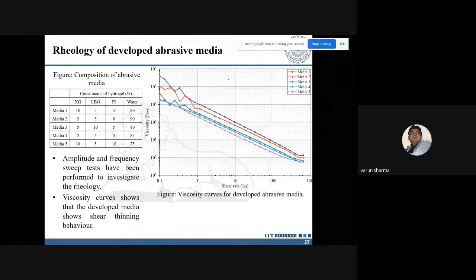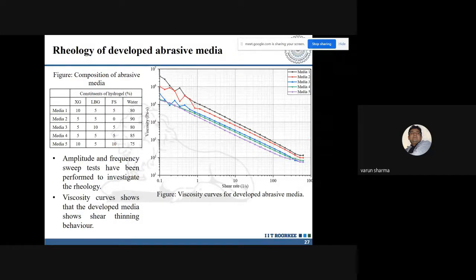We tried to characterize it using 5 different constituents: xanthan gum, locust bean gum, fumed silica, and water was used to get the desired constituents. Now, to determine the rheology, we go for the amplitude and the frequency sweep test. What we found is that as the shear rate increased, the viscosity decreased. That was what we were expecting, and it was characterized by the shear thinning behavior of that particular abrasive media. Now, this shear thinning was on a higher end as compared to the conventional natural rubber media that we were developing.